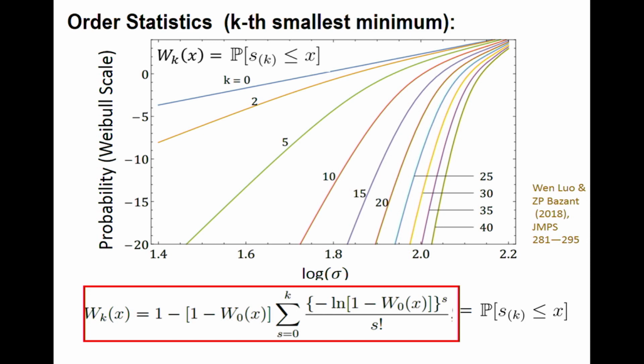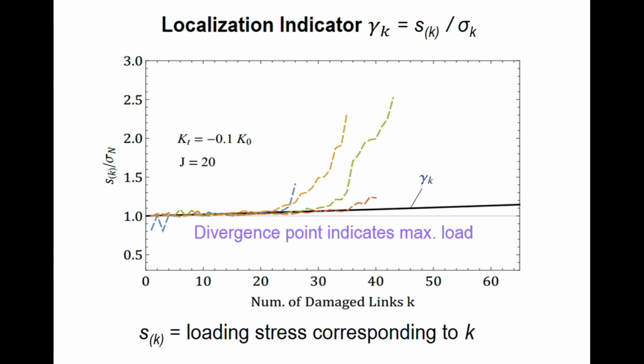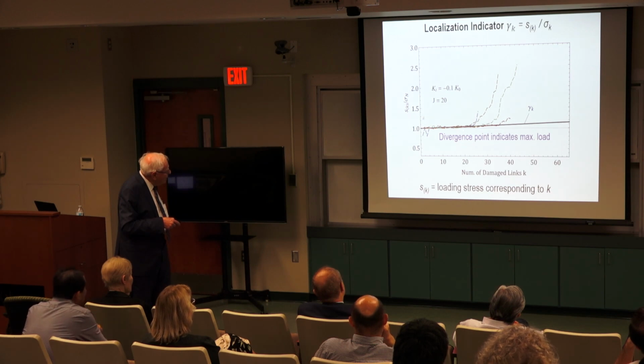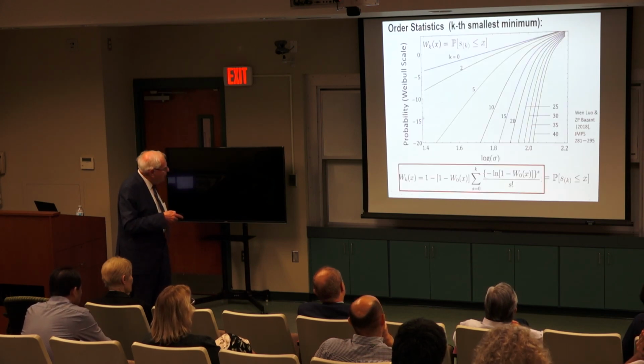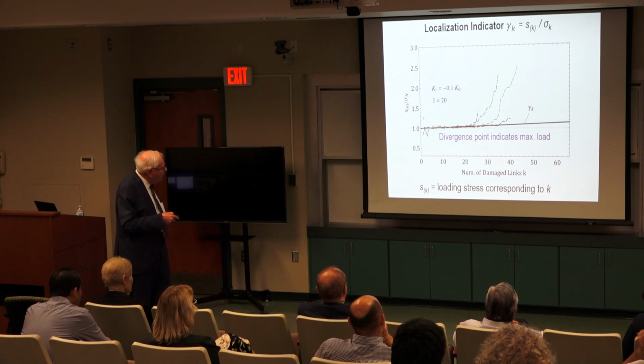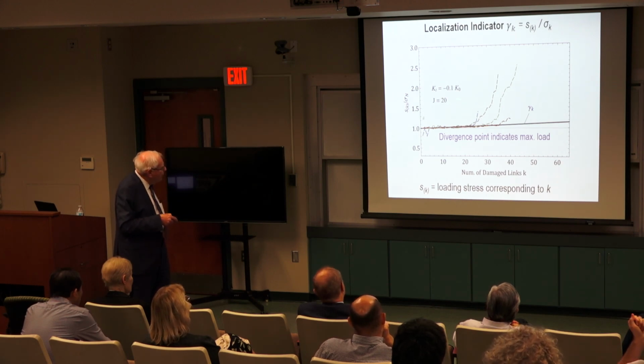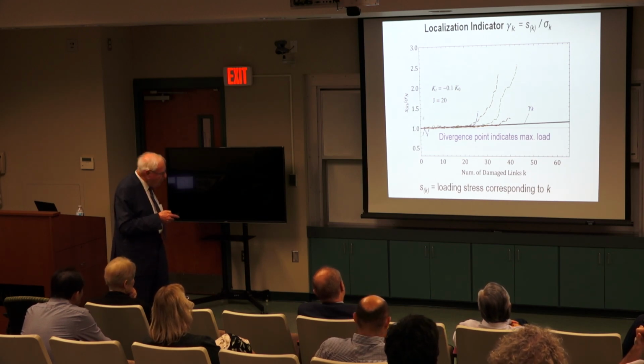In this case, you have no load deflection diagram. So how to estimate what is the maximum load? Is it this curve? Or is it the 5 or so? Okay, eventually we looked at the nominal stress change with the number of damage links. And at the beginning, it works, everything coincides, and suddenly they diverge. And we find that this divergence always corresponds to maximum load. So that tells you, in this case, that the number of jumps down, which gives maximum load, is 20, not something else.